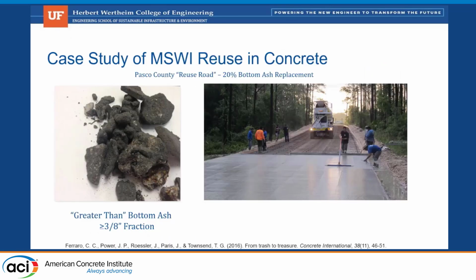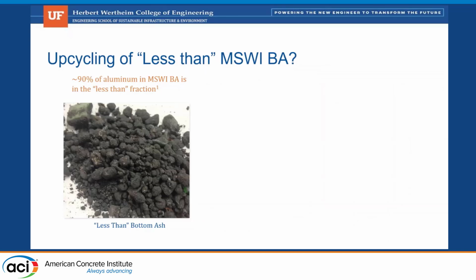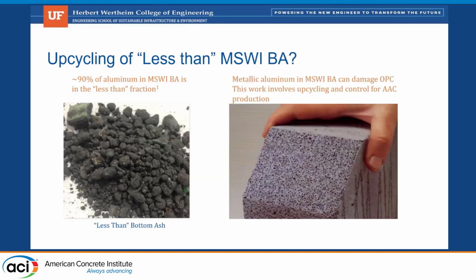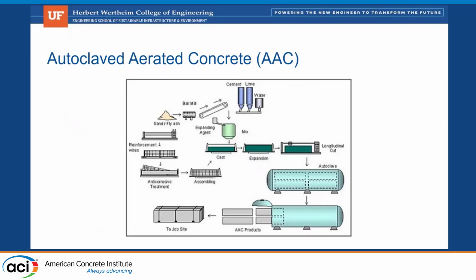So we're not going to use a fine MSWI in concrete production based on everything that I've experienced so far. We did do a case study where we built a road down in Pasco County out of that stuff. But again, we had to get rid of the less than stuff. So we have basically half of our MSWI ash not being reused. And that is, I think, one of the problems that bore us into maybe we can reuse it in another way. So how do we upcycle this stuff? We know that 90% of the aluminum is in the less than fraction from research, and I'll show some data that also confirms that. And we know that while metallic aluminum in MSWI can damage OPC structures, if we can control that, it actually can make an aerated structure. And so that's what this research focuses on.